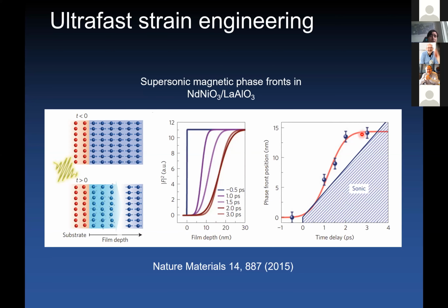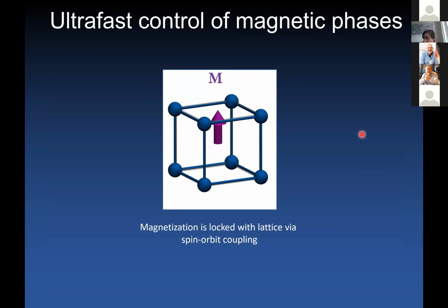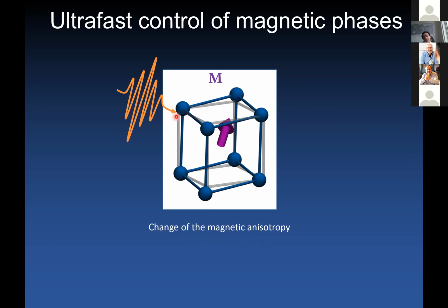So that's one application. The other application that I would like to discuss more in detail is the actual control of magnetic phases. So instead of melting a magnetic phase, the switching of an antiferromagnetic material to a ferromagnetic behavior driven by this type of physics. And the idea is again to rely on spin-orbit coupling. So we know that in this type of spin-orbit coupled magnets, the magnetization is locked to the lattice by spin-orbit coupling. So if you, with your laser, introduce some particular pattern of change in your lattice structure, you can induce a change in magnetic anisotropy, and therefore a reorientation of your magnetization.